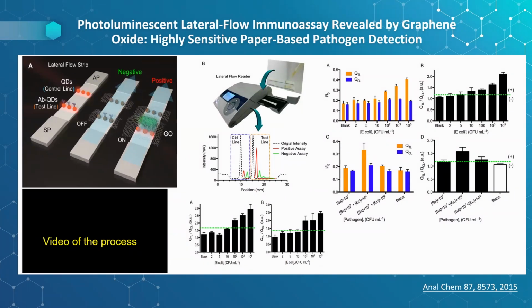I'll show you here how we design, for example, this nanobiosensor based on quantum dots. In fact, this is based on photoluminescence, where we use graphene oxide as a quencher of the fluorescence of quantum dots, this red dot here, for the detection of bacteria. This is a very interesting and very simple process in which we take advantage of the quenching capability of graphene oxide on the quantum dots, and you can see how simple it is to build these devices.